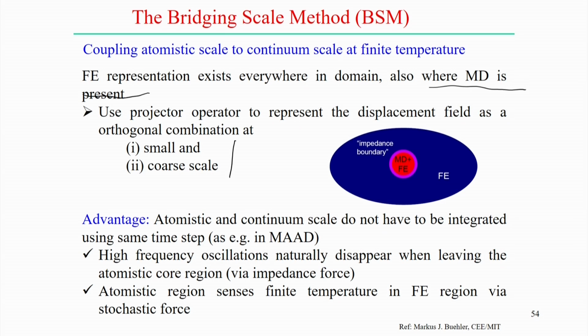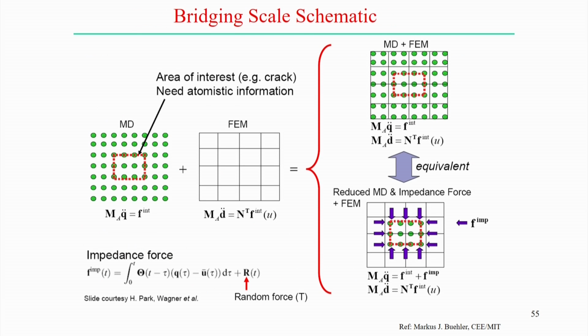But what are the advantages of this bridging scale method? The atomistic and continuum scales do not have to be integrated using the same time step, as is generally done in the MAAD scheme. High frequency oscillations naturally disappear when they leave the atomistic core region, via the impedance force. The atomistic region senses finite temperature in the finite element regions via the stochastic force. So this is another typical bridging scale method we generally follow in the multiscale modeling approach.